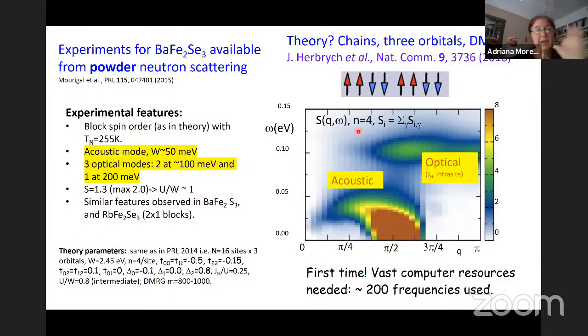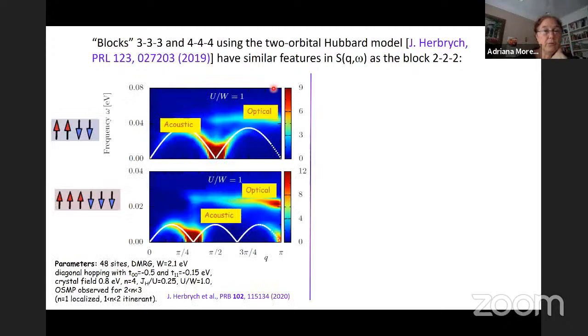Let's see what happens with S of Q omega as we go to larger blocks. These are the results I already showed you with size 2 blocks, and these are results in the regions with size 3 blocks. What you see is that this is again in agreement with the fact that the acoustic mode comes from long-range magnetic interactions between the magnetic blocks, because now the lattice size is 3 times what it was, the Brillouin zone gets reduced by 1/3, and here in the lowest 1/3 we see the strongest spectral weight.